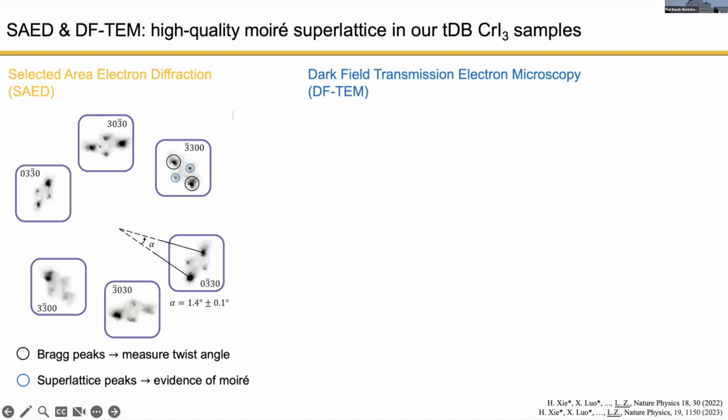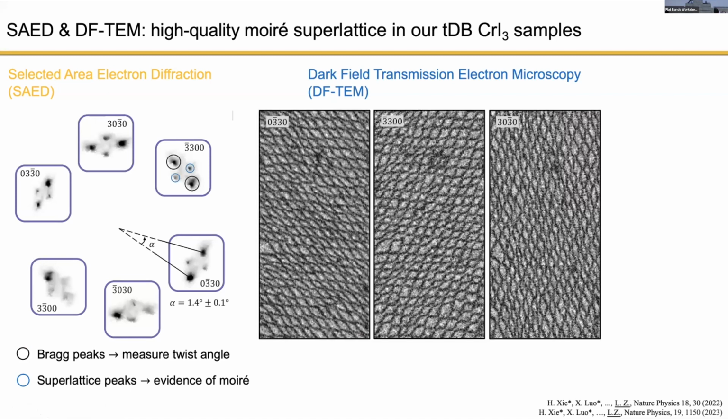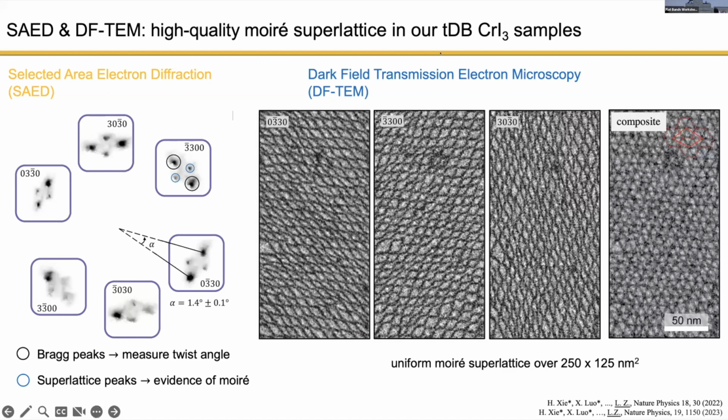Interestingly in this system, they are actually second order Moiré superlattice peaks. When they convert into real space, the wavelength they are seeing is actually 1/√3 of the actual Moiré superlattice. As to why a second order Moiré superlattice shows up, it still remains a mystery to us. We don't quite understand why it structurally behaves like this.